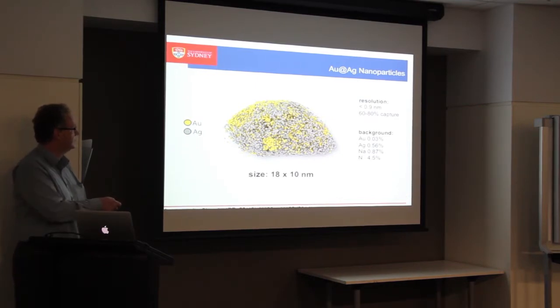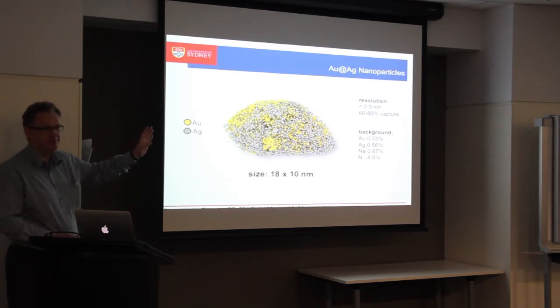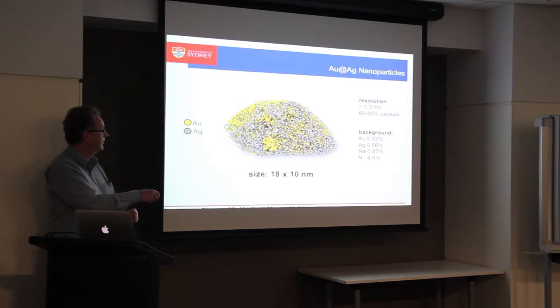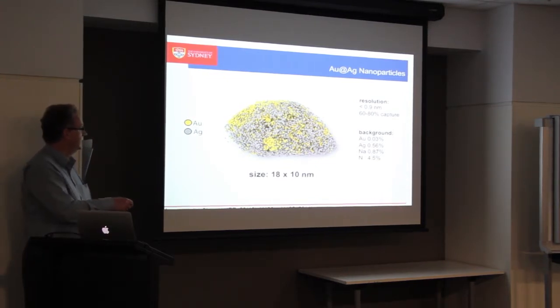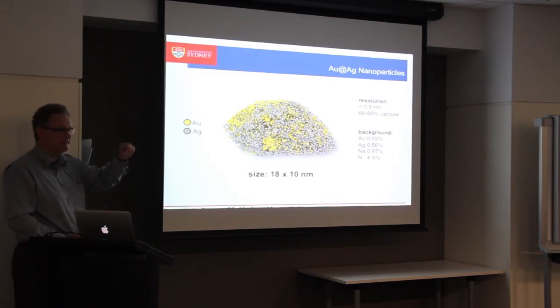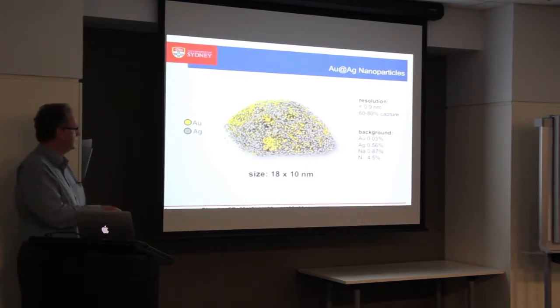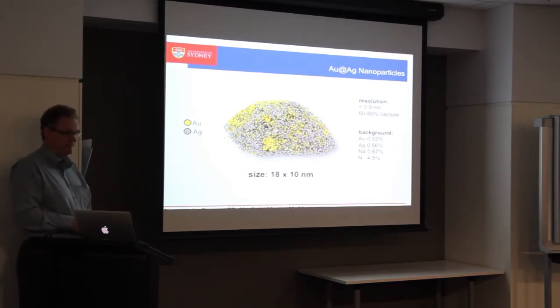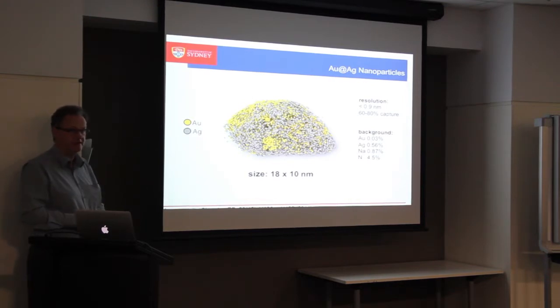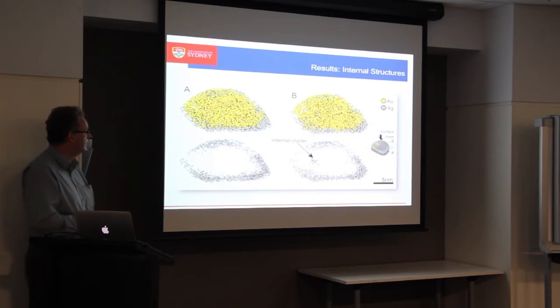Our resolution is actually about 0.4 nanometers — about 4 angstroms — though this slide is from a conference of experts so I under-promise here. We capture close to 80% of all the atoms flying off, which is why you see some void space — we know from where we didn't capture them, so those voids are meaningful. We are very confident in the assignment of gold and silver — there's virtually no background — and the amazing thing is we can even pick up sodium and nitrogen, which are very light atoms. Silver is colored gray and gold yellow.